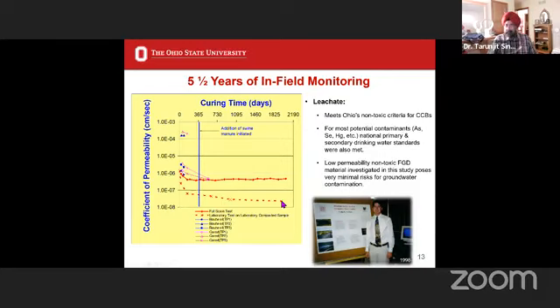What you will see is exactly what we see in clay. Remember what they say about clay: you measure the permeability of clay in the lab, and when you go and construct in the field, you will lose an order of magnitude. That's exactly what we saw. You can see that in the lab testing it was here, and in the full-scale field testing we lost an order of magnitude. It was 10 to the minus 7 in the lab and 10 to the minus 6 centimeters per second in the field.